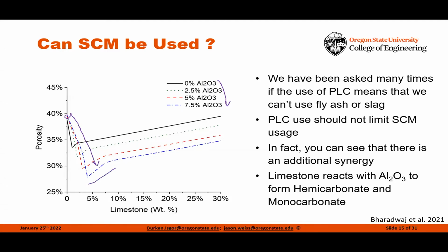And we're going to see that essentially that reduction in porosity gets us back to a similar performance as what we started with, and we're going to be able to go to a much higher limestone content in those systems. And this is along the lines of what Karen was talking about earlier with the LC3 cements. But this also starts to play into a lot of what we're talking about with using cellulose nanocrystals with slag and with some of these other materials, where we can now start to say we could actually utilize higher amounts of limestone in these systems, provided we have a reactive alumina.